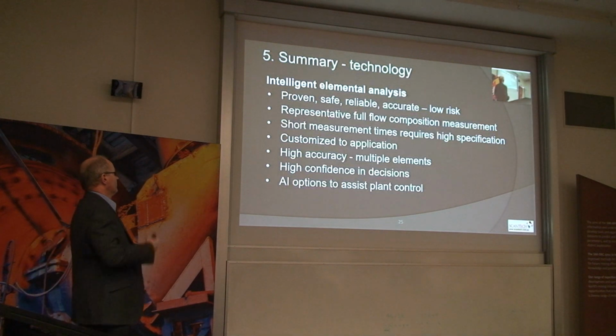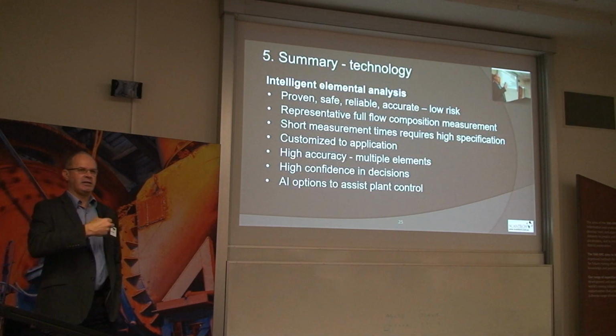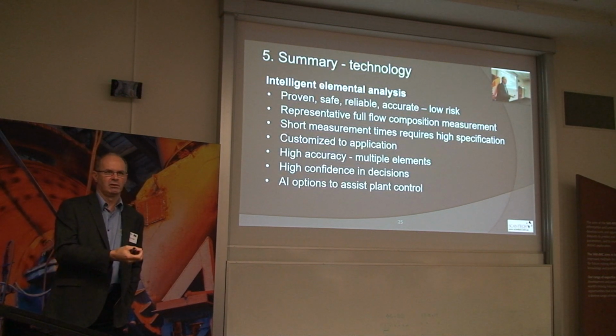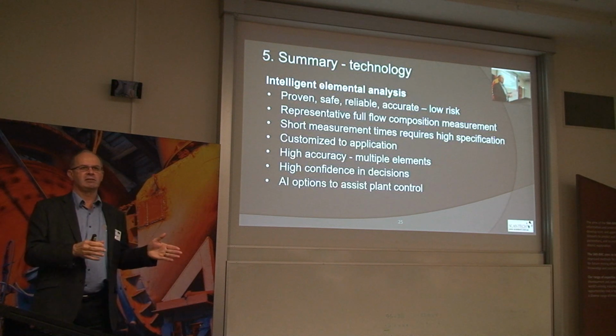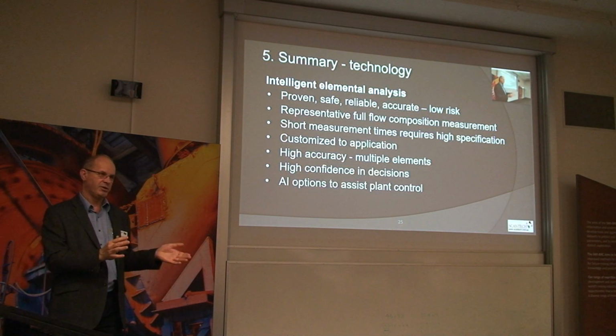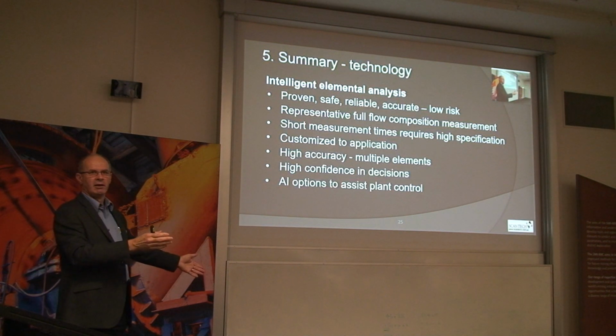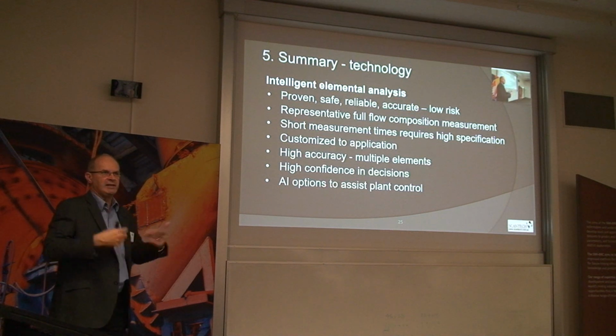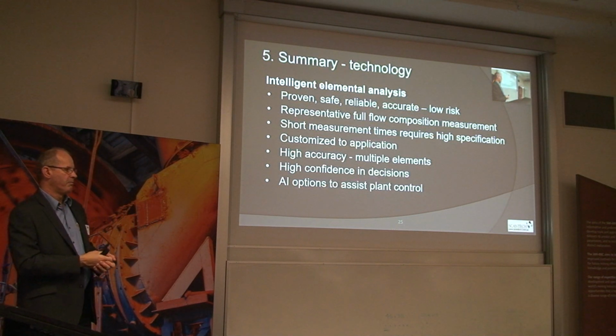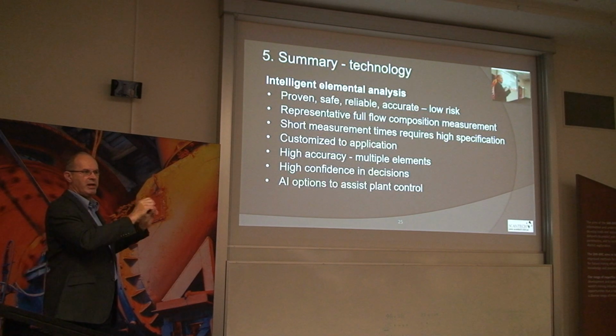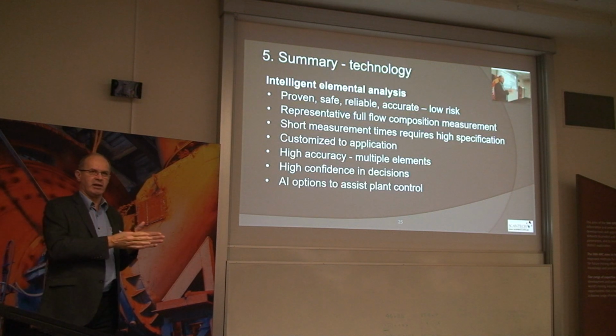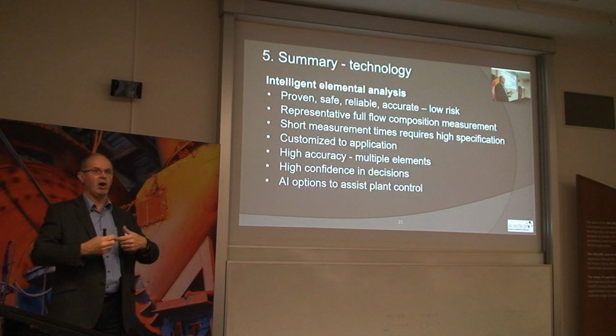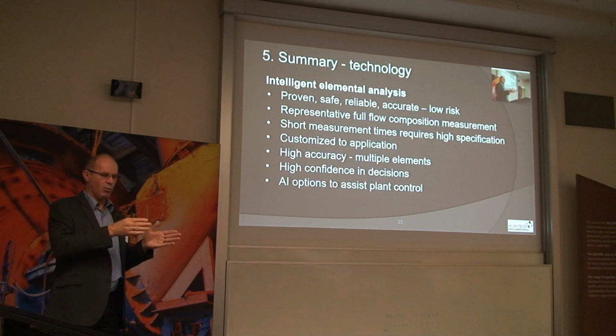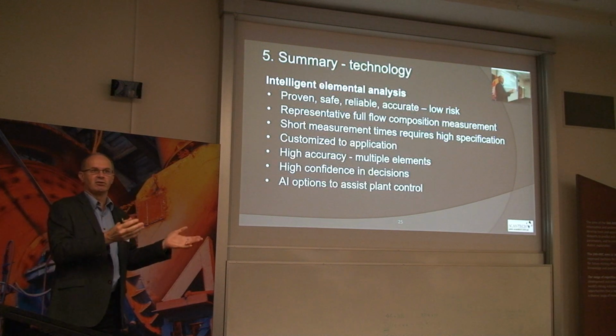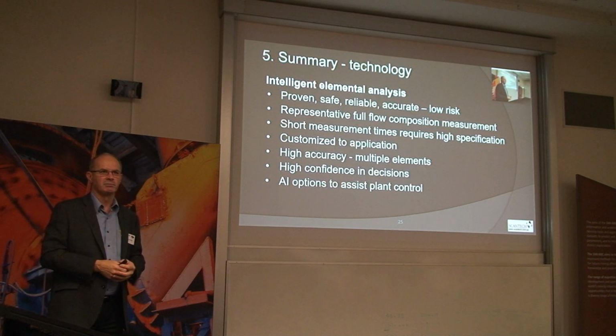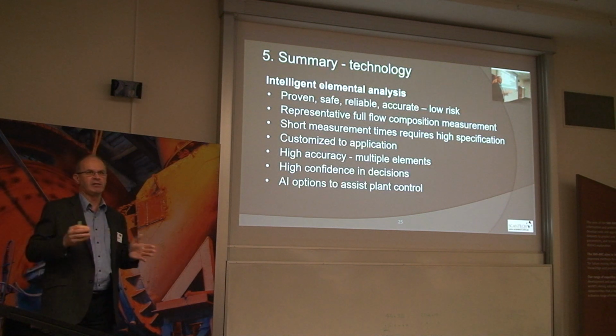So just summarising, what we're trying to do is supply a technique that's customised for this application. For bulk ore sorting over 30 seconds, it's a very high specification. It's a different specification to the Sepon one where we're measuring for 2 minutes, because over 2 minutes you can use fewer detectors, for example, and you're averaging over a longer period of time. So that measurement can be quite accurate. When you come to 30 seconds, you're sacrificing time, and time means the number of counts. So to get more counts over a shorter period of time, you need more detectors or a larger source or some software modifications. That's why the systems are different for each application.